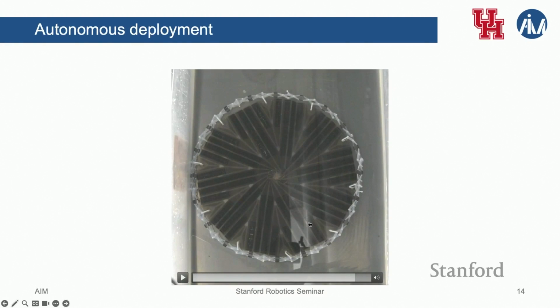And the other point is, because of the distributed nature, okay, let me see if I can do this. Okay, there's many defects. If you look closely at the deployed state, many things have broken. Not broken, as in, it was our first or second attempt of the same structure, and because I'm not the best designer in the world, there are many things that have fallen apart. But because the actuation really comes from the strain energy of the material everywhere, every part can deploy in a sense by itself. There's nothing antagonistic against the deployment of itself. So it's very robust in a sense that it does not depend on a single point of actuation to deploy this thing. So that's the first shape-changing system that utilizes shape memory polymer to change the shape.